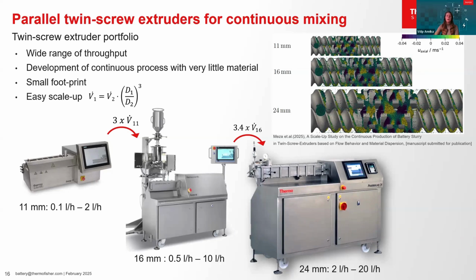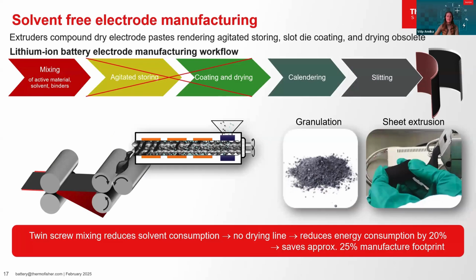Now let's have a look onto dry processing in the next slide. The conventional manufacturing of lithium-ion battery electrodes involves mixing active materials and additives with a solvent to create a slurry, coating it onto a current collector foil, drying, calendering it to the desired density and height, and laser slitting the electrodes. Twin screw mixers offer the potential to mix electrode materials with binders and additives using little or no solvent due to higher shear energy input.